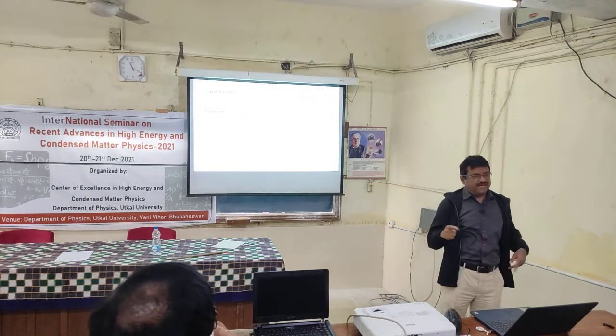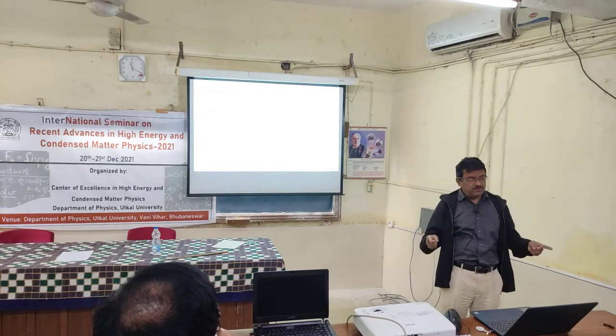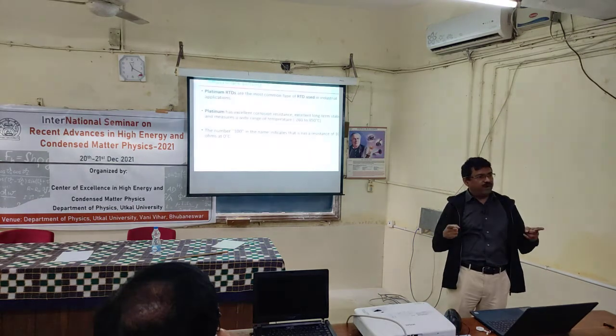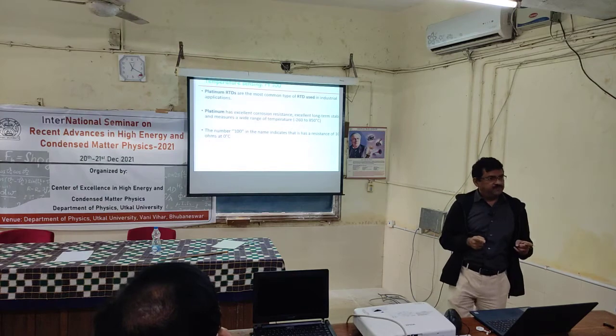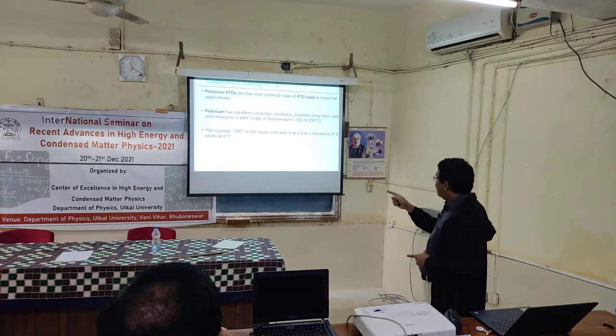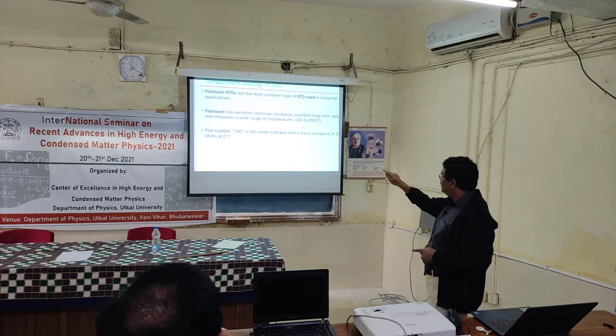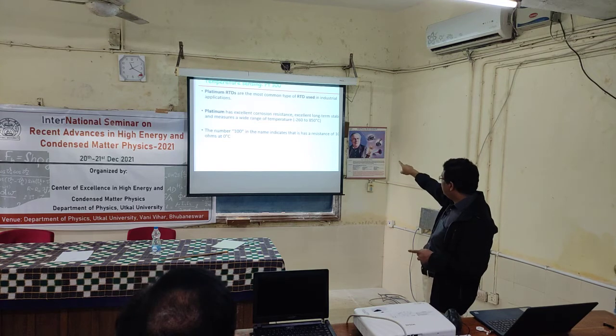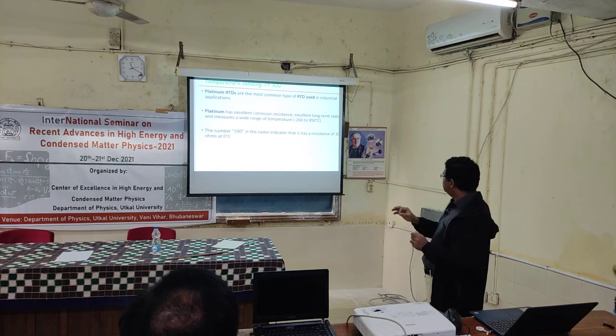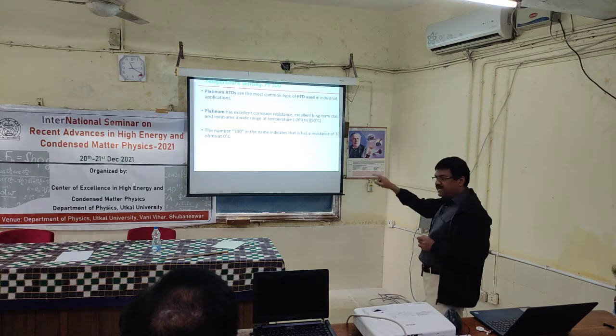So in that range, this platinum resistance thermometer can be used, and the accuracy is about 0.1 degrees centigrade. And the number 100 in PT100 denotes that the resistance of the platinum wire which is used is 100 ohms at 0 degrees centigrade.